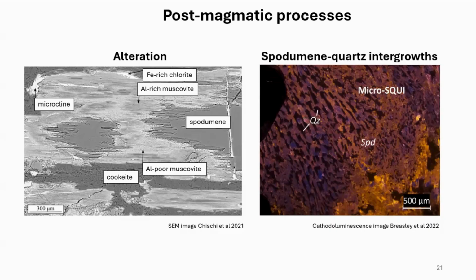What happens is when you put that, I'll back up. So spodumene itself, surprisingly, is insoluble. So there's something called calcination. For those of you that know a little bit of metallurgy, calcination is you heat something up to high temperature. So if you heat spodumene up to 1,000 degrees C, it goes from alpha spodumene to beta spodumene. If you take alpha spodumene and put it in sulfuric acid, nothing happens. Beta spodumene changes its structure. You think of entropy as you heat something up, things become more random. You're changing the crystal structure. So the beta spodumene is then soluble in high temperature sulfuric acid. That's how they process most spodumene ores.